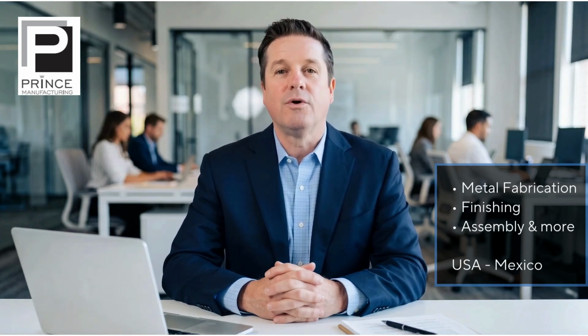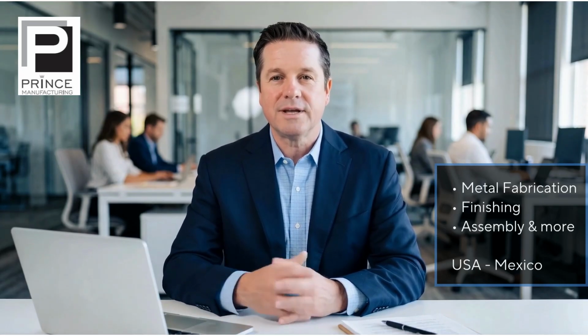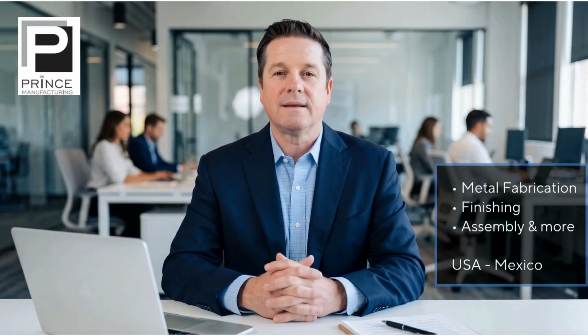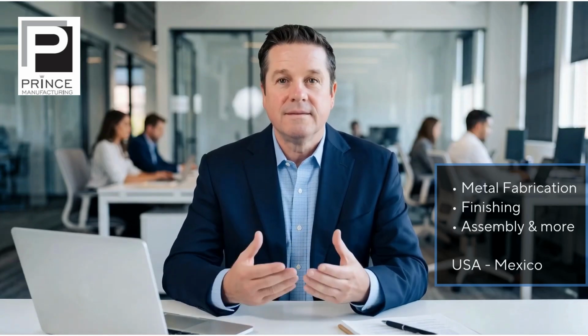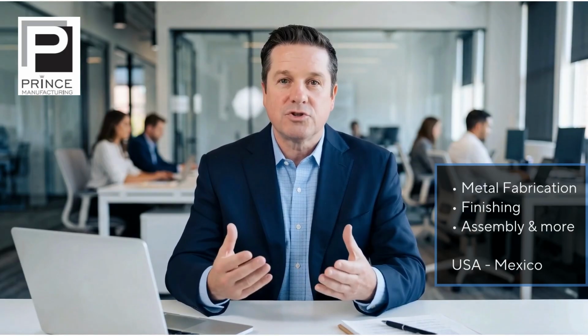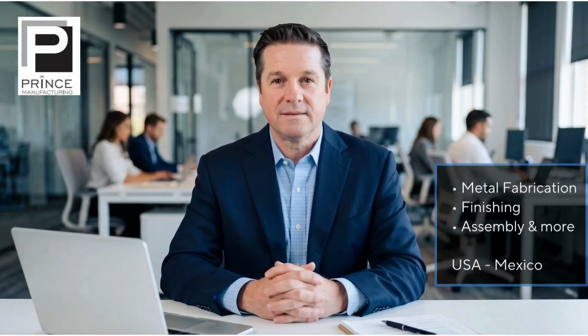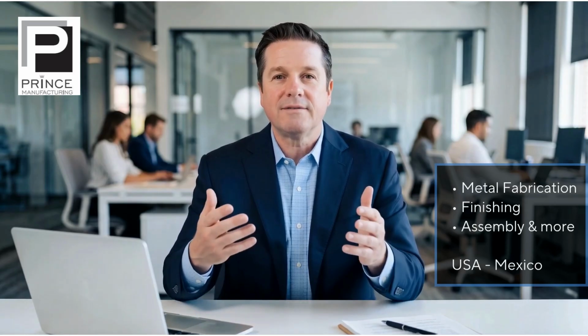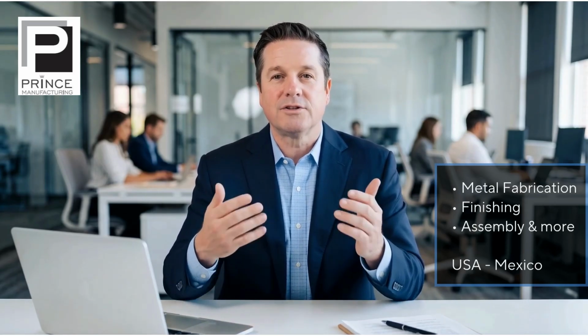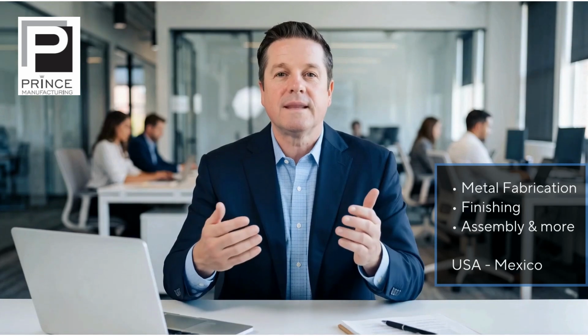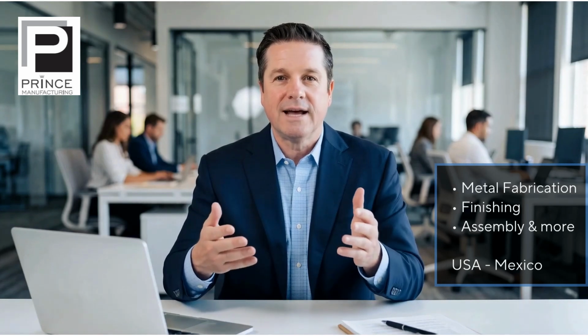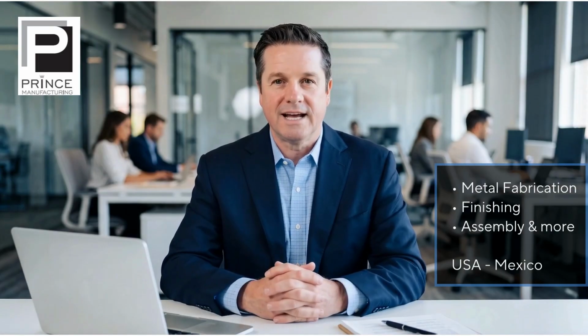And when someone gives you a salt spray number, ask what failure actually means. Is it white corrosion on the zinc? Red corrosion of the underlying steel? Blistering? Corrosion creep from a scribe? Or loss of adhesion? The substrate, pretreatment, coating thickness, sealer, edge condition, specimen preparation, and test method all affect the result. Do not compare coatings based only on one advertised number. Ask what standard was used. Ask what coating thickness was applied. Ask what constituted failure. And ask whether that failure mode represents the actual application.